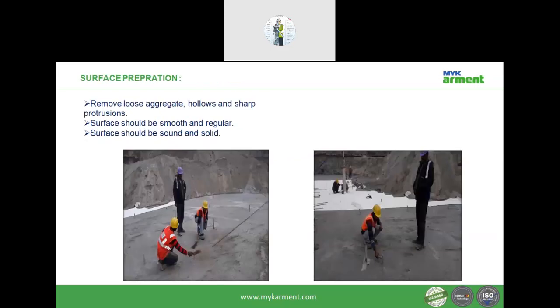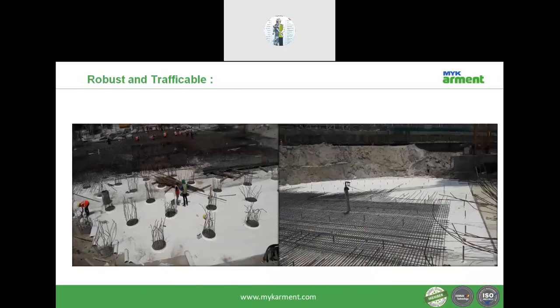This is about the surface preparation. There should be no sharp edges. The surface should be smooth and regular, and it should be sound and solid. Then it is a robust and a trafficable material. Once you lay this HDPE membrane, you can directly leave it exposed for 36 days, and then you can even lay the reinforcement because it has a higher puncture resistance of more than 880 newtons. But you need to take care that you don't drag the reinforcement on the HDPE membrane.